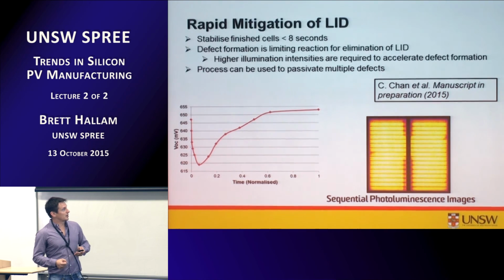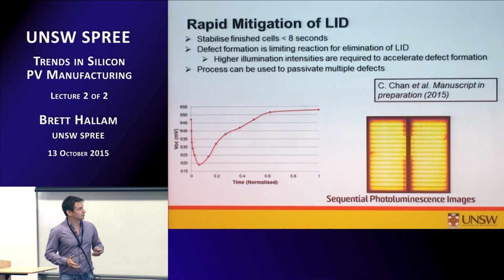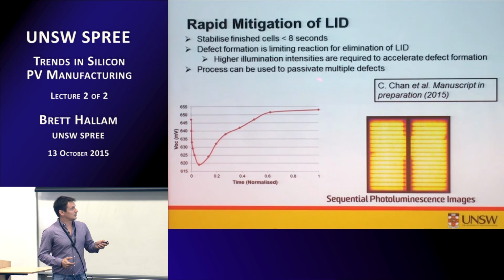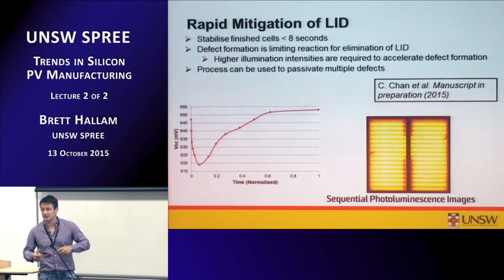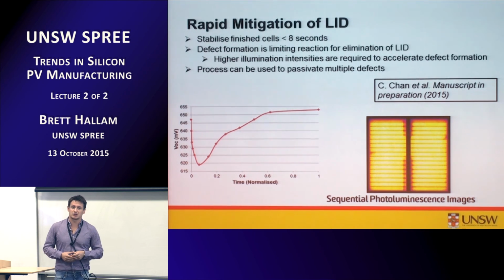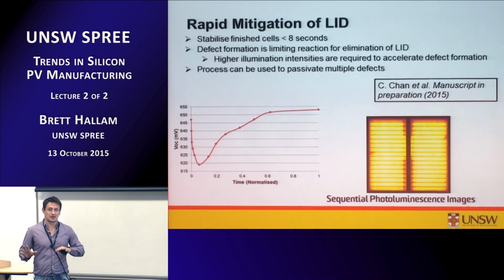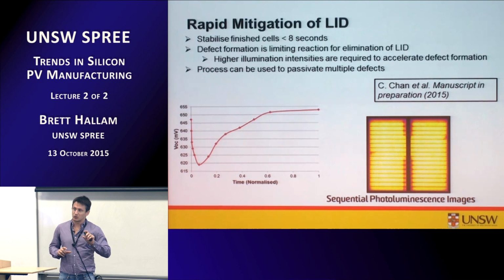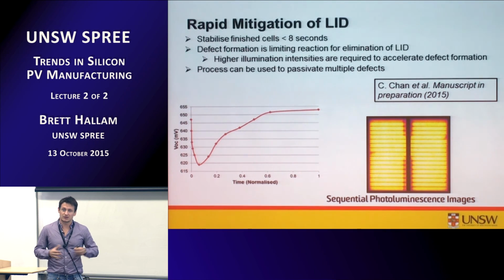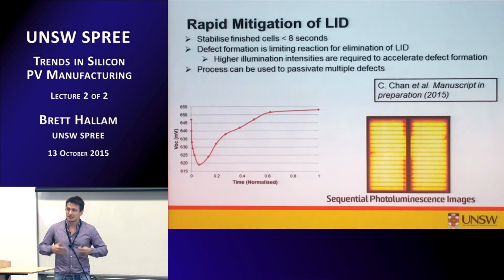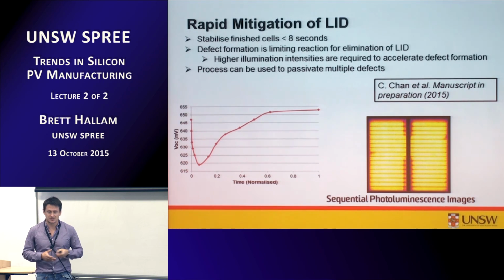And one exciting aspect of our process is that we end up with higher stabilized VOCs and efficiencies than what these solar cells are coming off the production line. Because our processes aren't necessarily just looking at the boron oxygen defect, they can potentially be passivating other defects in the device as well. And so we think the next generation of these LID stabilization tools will be targeting more than just the boron oxygen defect or the light-induced defect, etc.